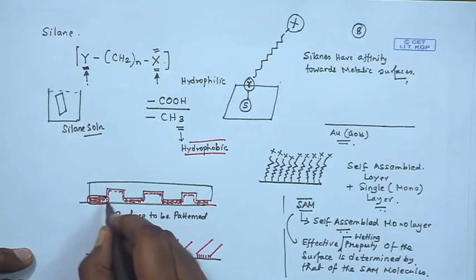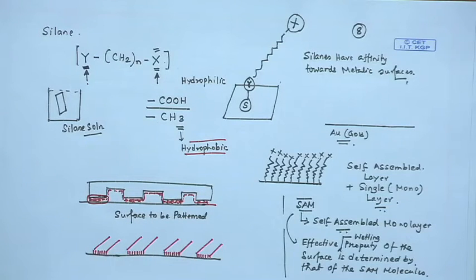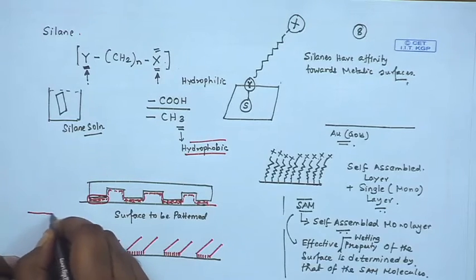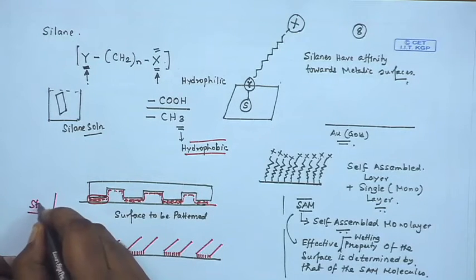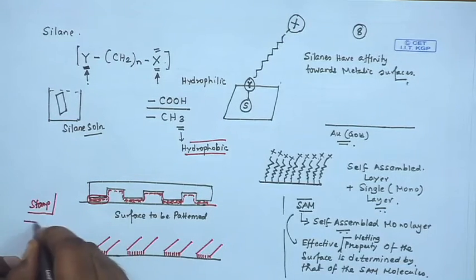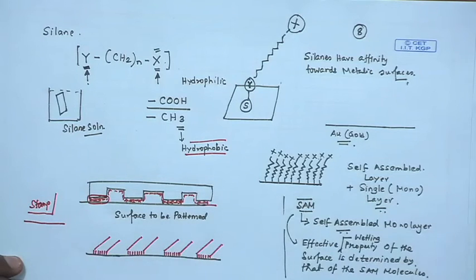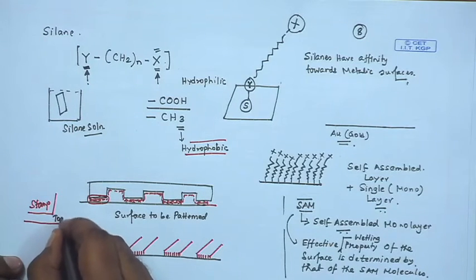Unfortunately, the silane molecules are then completely stuck on the stamp surface, and they actually need this liquid meniscus through which they can migrate and undergo this self assembly. But if the liquid meniscus is absent, if the stamp comes in too dry, then the transfer does not take place.